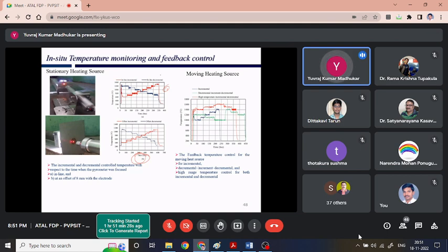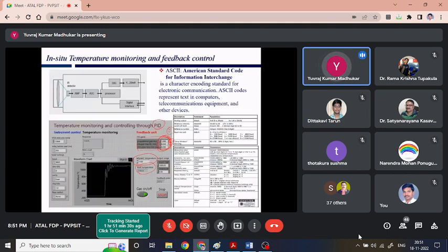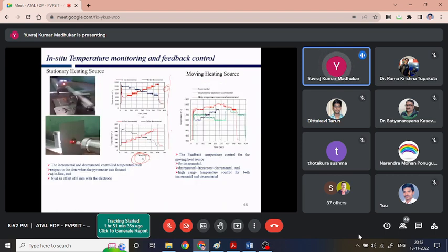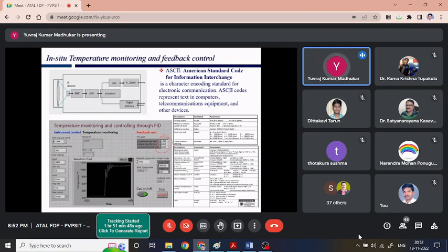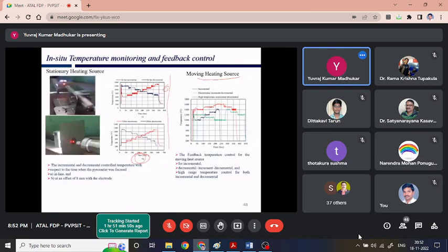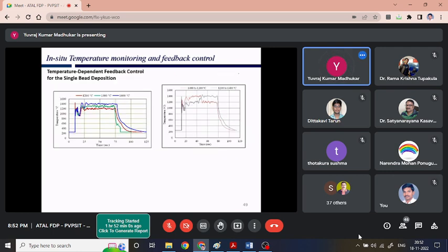Now, once we are able to reach this state and we are getting some value of these PID constants, it is time to move the heat source without any deposition. Just move the heat source and again optimize if something is required to optimize these constants. And of course, with a certain hit and trial method, a little bit of up and down, we are able to achieve it. Once we reach this stage, possibly now it is time to deposit a single